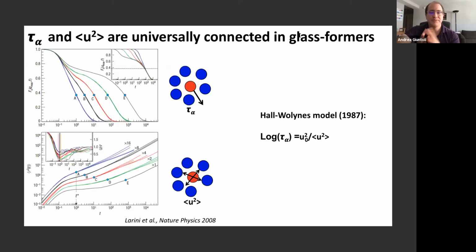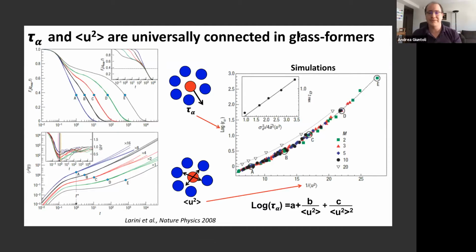It was in 2008 that my PhD advisor, that was before I joined the group, came out with this simulation paper showing that for different systems, here you can see A, B, C, D, E. These are not 5 systems, they are a lot of different systems that are tuned so that you have 5 different groups with these 5 different values for the relaxation time. They also share the same Debye-Waller factor. And by varying a lot of parameters in the simulation, you see that they all can be scaled onto a master curve where the behavior of log tau alpha is not just linear with 1 over u squared, but it has also a quadratic term due to the fact that not all cages are the same. The system is highly heterogeneous. So you have to take into account the variance of the different cages, which leads to a quadratic order.